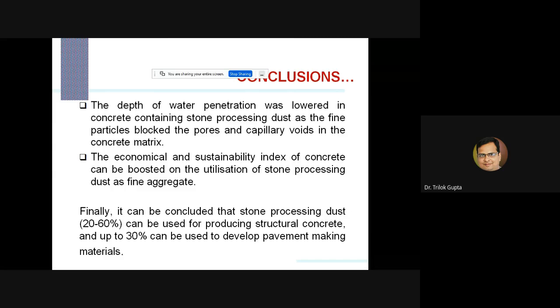The depth of water penetration was lowered in the concrete containing stone processing dust, as the fine particles block the pores and capillary voids in the concrete matrix. The economic and sustainability index of concrete can be boosted by the utilization of stone processing dust as fine aggregate.